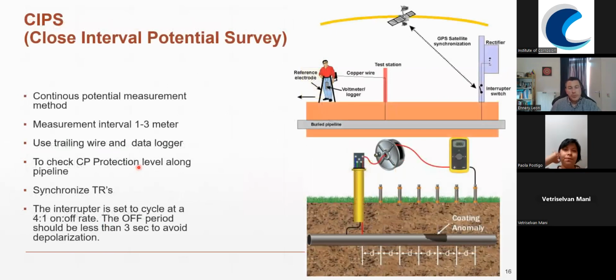Then the second survey that we can use is the close interval potential survey, or CIPS. This one is a continuous potential measurement method. We usually have a measurement every 1 or 3 meters. Usually we choose a gap between the readings according to the depth of the pipeline. We need to use wires and data loggers, of course, to record the readings. It's used to check the CP protection level along the pipeline. We need to synchronize the TRs. And as I said, we usually set the interrupter at a rate of 4:1, meaning that the off period should be less than 3 seconds to avoid depolarization.